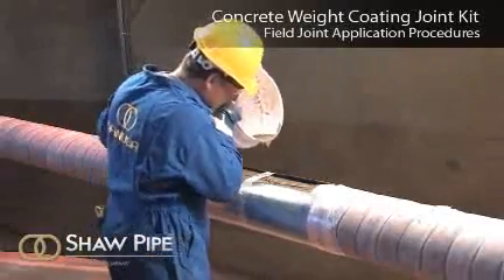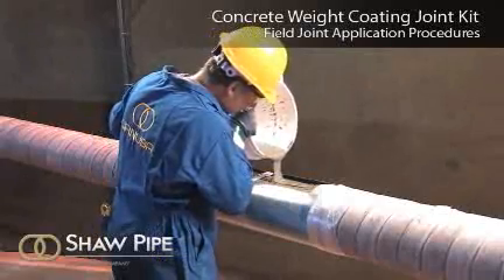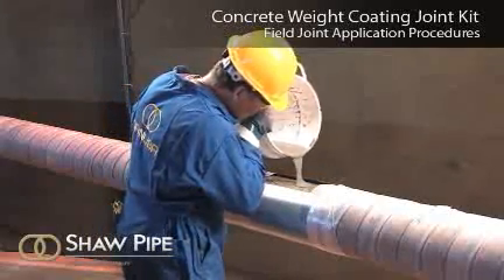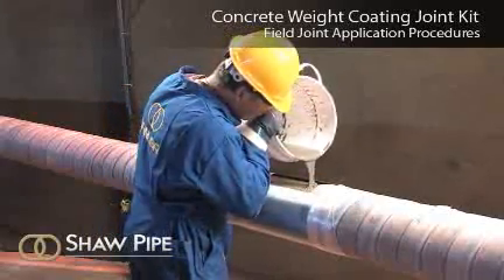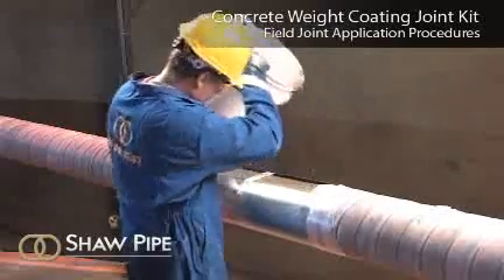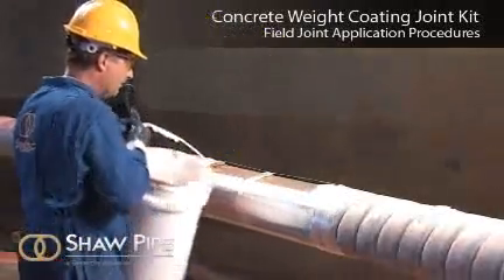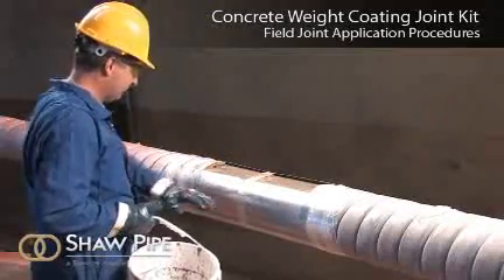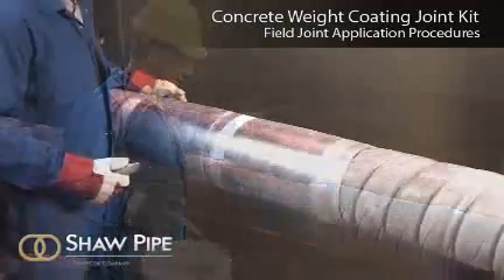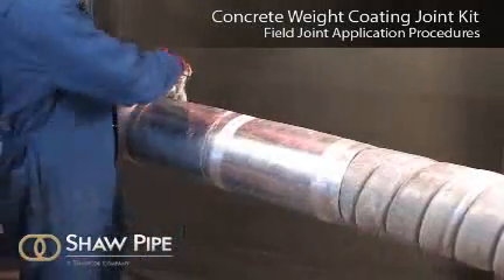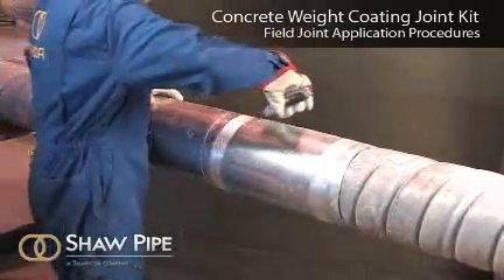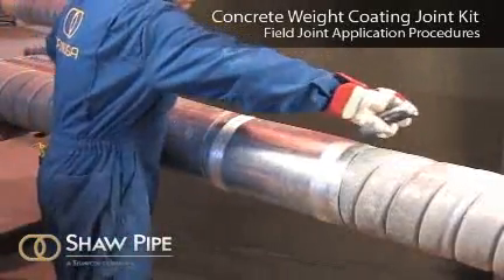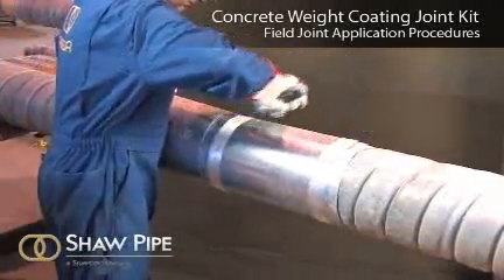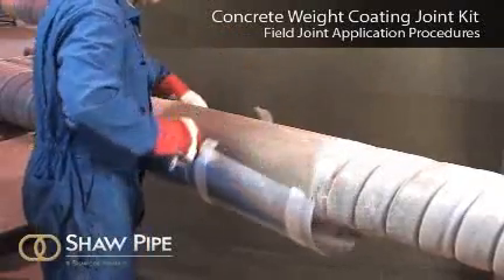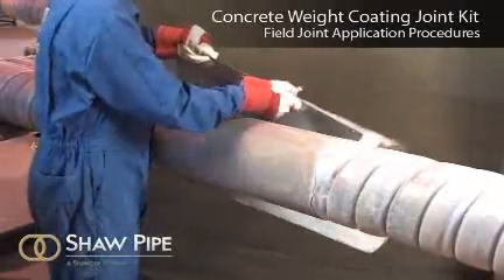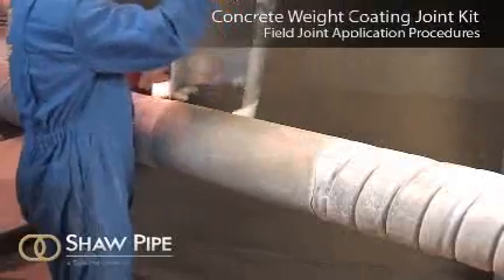Pour the grout into the gap at the top of the sheet metal form until the joint area is full. Light tapping on the outside of the form during pouring will assist the grout to flow around the pipe and thus reduce the chance of voids. Once the joint is full, strike off any excess material and cover the exposed grout with plastic tape or sheeting to prevent moisture loss. Loss of moisture will inhibit proper curing. After 24 hours, the form can be removed if required.